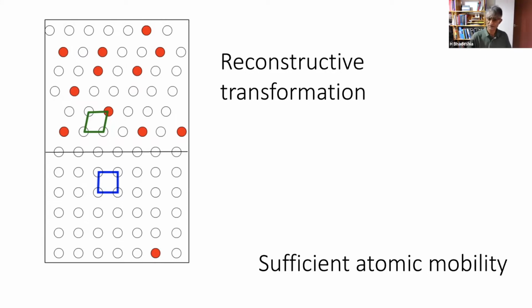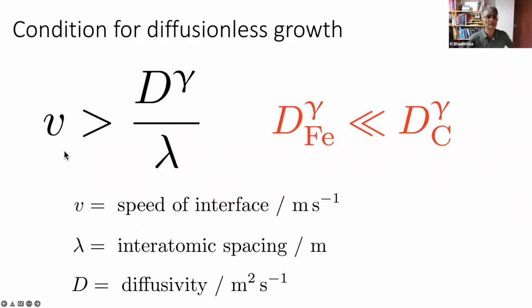Okay, so what are the conditions that favor a displacive transformation over a reconstructive transformation? Well, there's a very simple equation here. If the velocity of the interface exceeds this term, and this term is effectively the velocity of an atom which moves by diffusion, because D has units of meters squared per second, and lambda is an interatomic spacing, which is meters, so meters squared per second divided by meters gives you a velocity. So this is the diffusion velocity, and this is the interface velocity. So if this is greater than this term, then we get a displacive transformation. And atoms will be trapped either in the product or the parent phase, whether they like it or not.